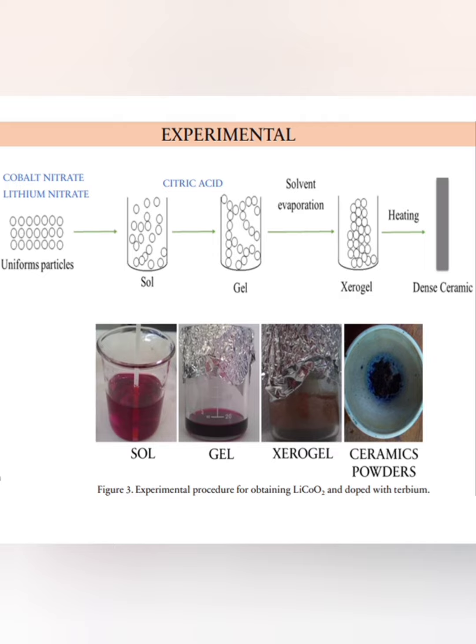The sol-gel synthesis route starts from uniform particles of either metal salts or alkoxides and is based on hydrolysis and condensation reactions for the formation of a solid, and subsequently a three-dimensional network generated by an increase in temperature and a gelling agent. It is the method chosen for the purpose of the project. Nitrates were used as precursors and citric acid for the formation of the gel.